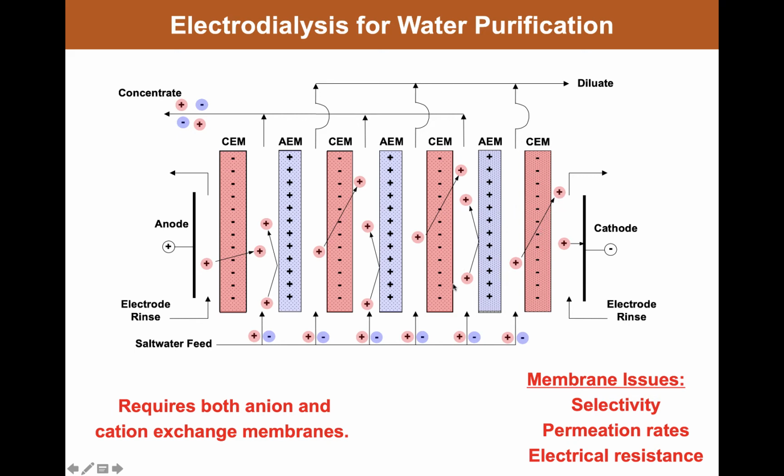On the other hand, the cations are rejected from the anion exchange membranes. Having this positive charge in the anion exchange membranes acts to inhibit the sorption and then transport of cations through these membranes by a process known as Donnan screening, which we'll talk about in a moment. But you can think about it simply as opposite charged ions attract, and so the cations want to go into the cation exchange membrane.